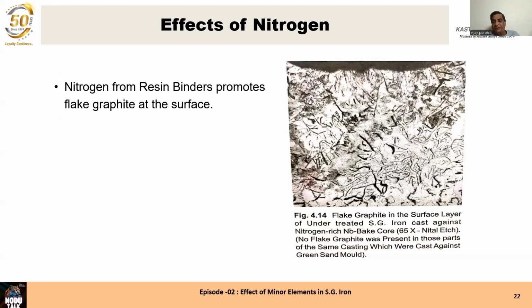Nitrogen forms flake graphite. Nitrogen comes from nitrogen containing binders and resins used for making the cores. Nitrogen is one of the elements which is very difficult to detect. The only way you will know nitrogen is present is by looking at the microstructure and the flake graphite, whereas where the casting is cast against the green sand mold, where there is no nitrogen present, you again have beautiful ductile iron structures. So nitrogen from resin binders promotes flake graphite at the surface of the casting, and these nitrogen layers may not get removed even by 3 millimeter machining. So you have to be careful that you coat your resin coated cores with some kind of a coating which will prevent the effect of nitrogen in forming flake graphite.